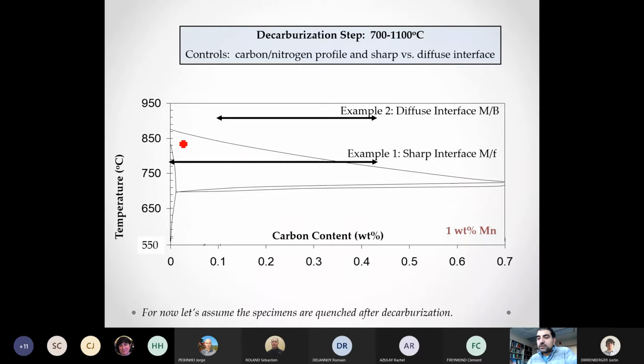And I put a schematic here of an iron 1% manganese carbon phase diagram. And depending on what temperature we choose for the decarburization, we can control whether or not we have an interface in the material. If we decarburize the steel with 0.04 carbon, so this is 0.04 carbon, at let's say 775 or 780 degrees C, you'll notice there is an alpha region here at the surface. So if there is zero carbon on the surface, we will make a ferrite layer on the surface, and that ferrite layer will grow into the steel. So decarburizing at this lower temperature will give a steel with a sharp interface between the low carbon region and the high carbon region.